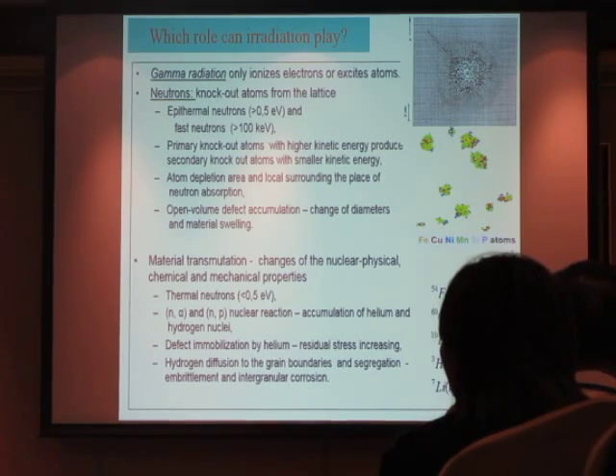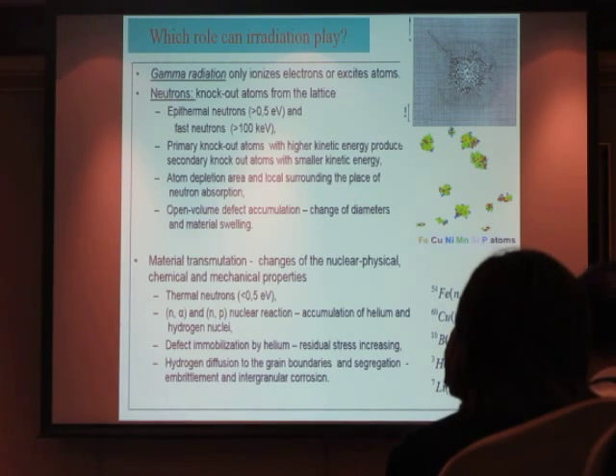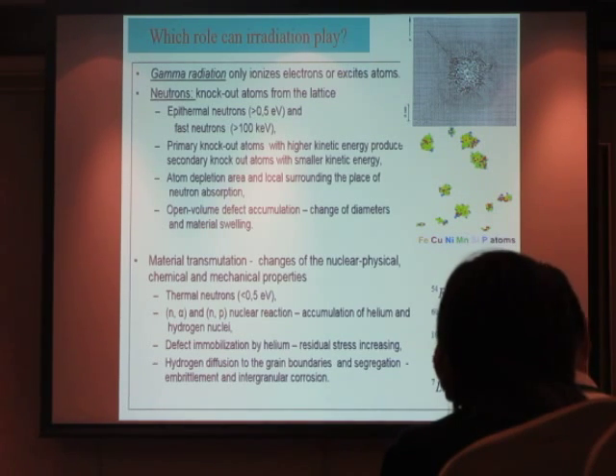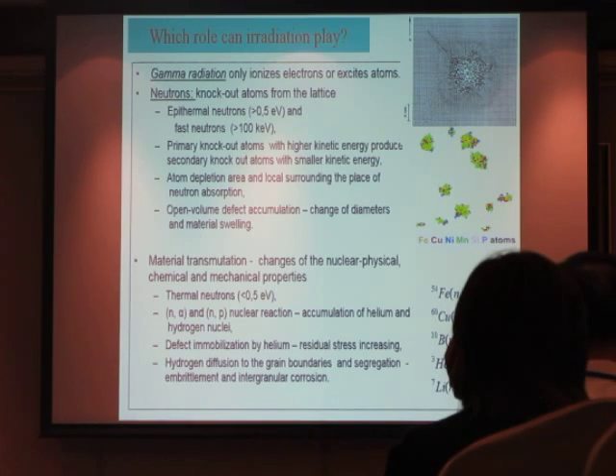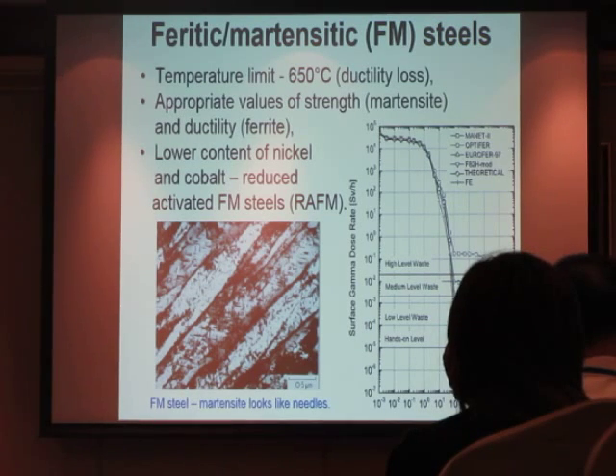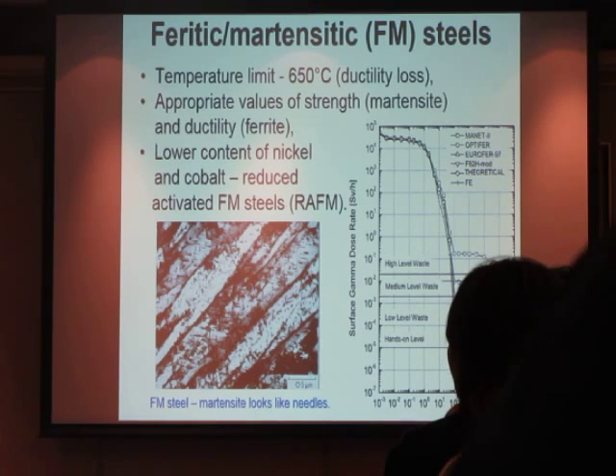What is being studied is embrittlement. Embrittlement is the creation of defects, which are mostly moving to the dislocation, to some boundaries, which makes an obstacle against the plastic deformation of the material. So therefore, these knockout atoms are crucial from the mechanical point of view for the embrittlement. I mentioned that chemical composition is very important, and when we speak about decommissioning, we need to know when we can cut this reactor pressure vessel, and it depends on the cobalt-60 inside. And therefore new materials are developed, mostly to access the reactor pressure vessel later.